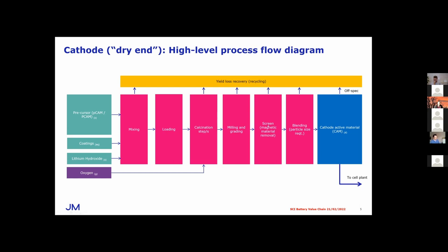Throughout both of the processes for precursor and cathode material production, you generate yield losses. These can come at many of the different steps, including where you have off-spec material that doesn't meet the quality or the specification for the customer. And these products can be recovered, and they're potentially easier to recover than, say, end of life or value chain material that comes from the cell or pack step, because you've yet to combine them with other metals or other products or any organic or fluorine containing components of the later steps. So we expect to see an ecosystem that is set up to recover a lot of these yield losses as the industry grows in size.